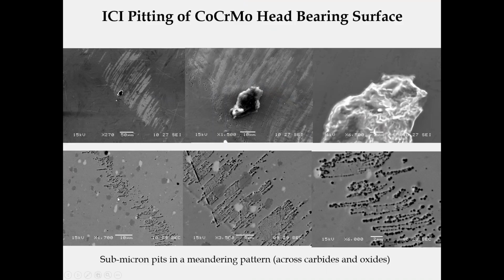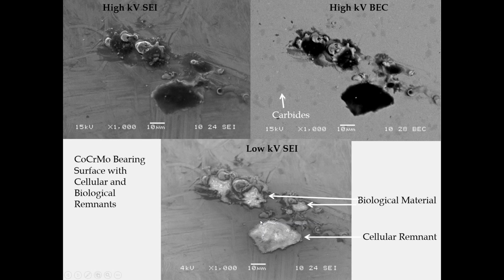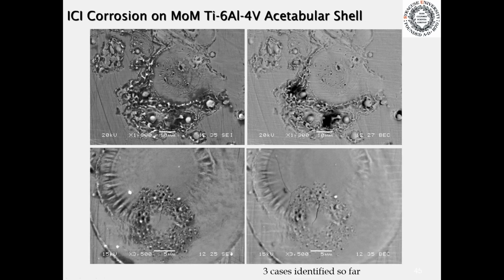Also, we've seen examples on bearing surfaces where you see selective pitting going on and evidence of remnant biological species, perhaps biological cells, that have caused this pitting attack, where the pits are actually moving across carbides and other parts of the alloy itself and creating the conditions where corrosion of that substrate can occur. And these are just some other examples.